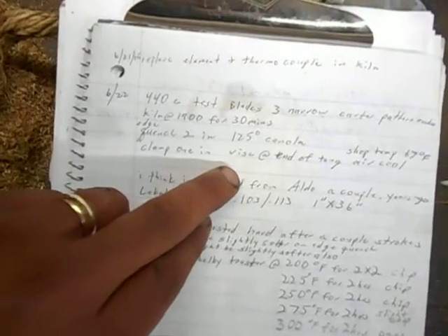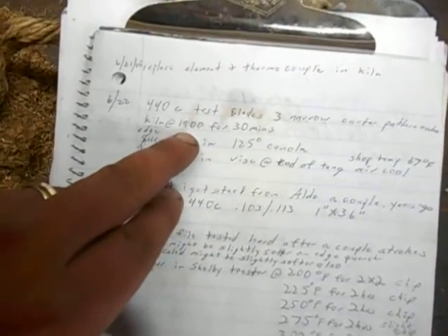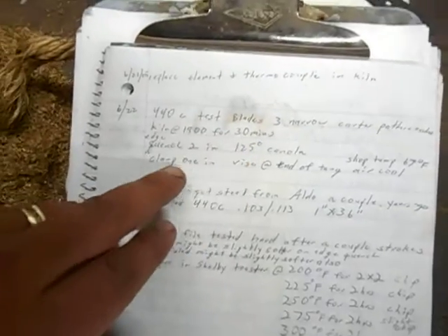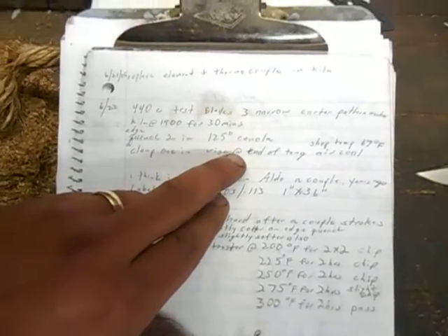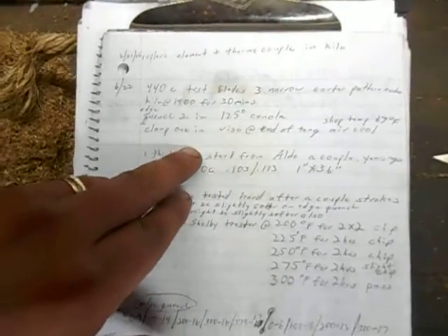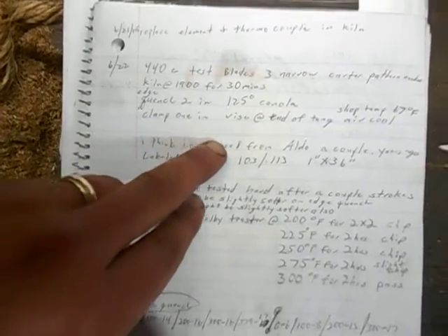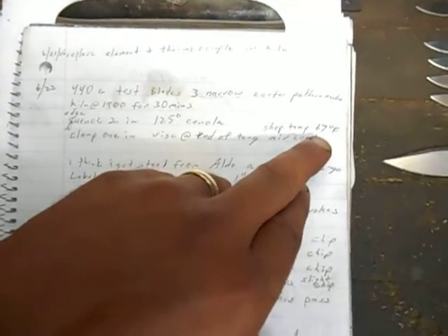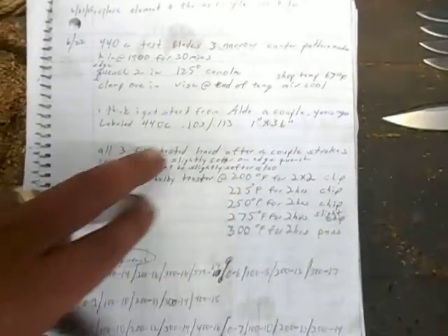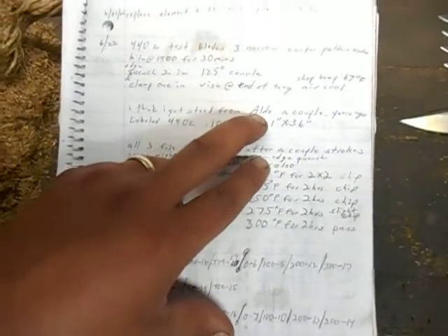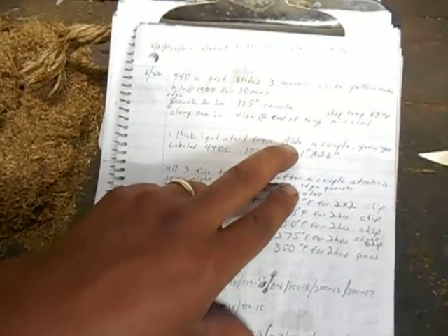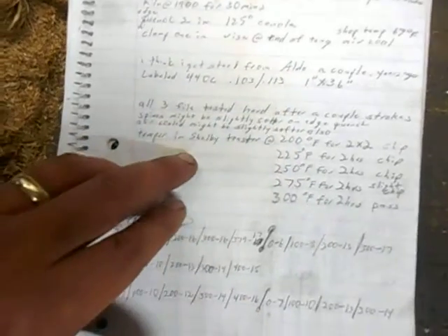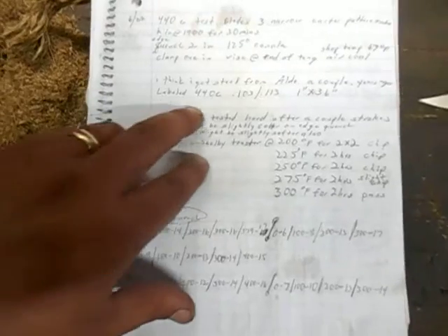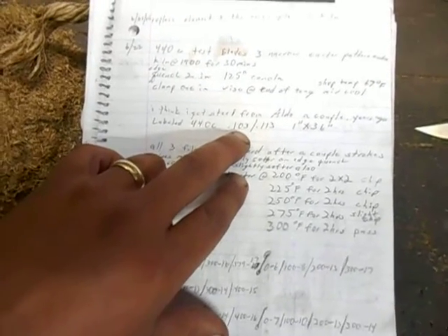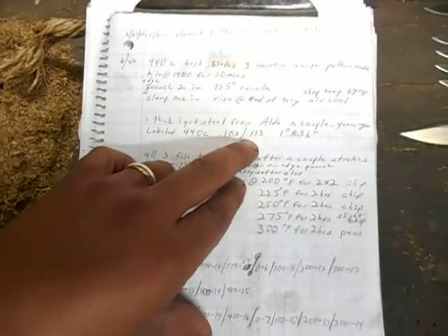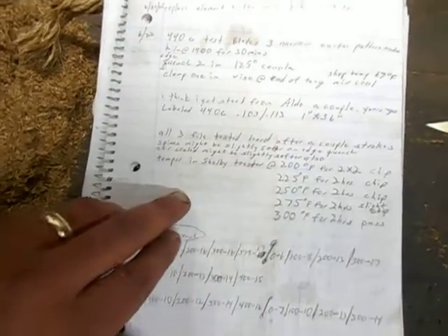But anyway, these blades, I put them in the kiln at 1900 degrees for 30 minutes. I edge quenched 2 of them in 125 degree canola oil, and then the third one I just clamped tip up in the vise and let it air cool. The shop temperature was 67 degrees that day. I think I got that first piece of steel from Aldo over at New Jersey Steel Supply. A quick web search would find him, and it was labeled 440C, 103 thousandths to 113 thousandths, and it was a 1x36 inch piece.